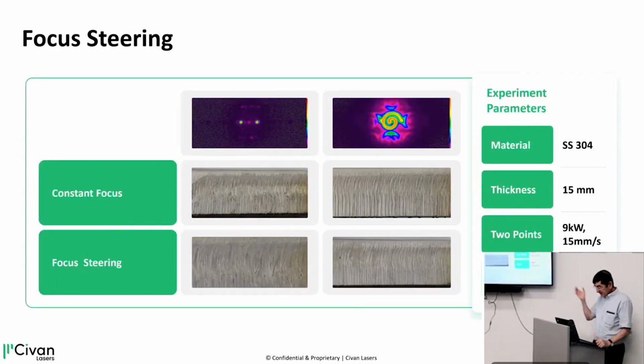And this is an example of cutting. You see here a cross section of a cut, where on the top it was fixed focus, and on the bottom it was focus steering, and you see much smoother all the way down. This is 15 millimeters, and no dross at the bottom because you have the hot spot all the way at the bottom. And of course, in welding it is the same thing, just difficult to show this in welding, but also in welding, if you want to control everything that's happening in the depth of the weld, you can do the focus steering.